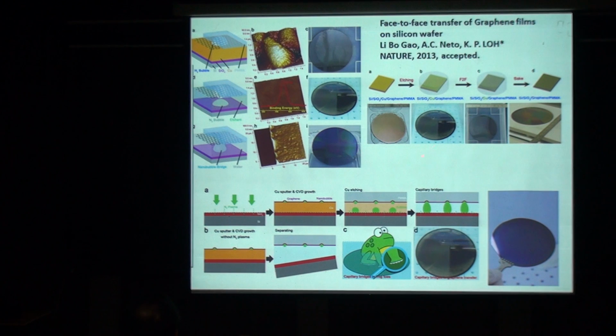Another interesting application which we just published in Nature is the fact that the bubbles have very serious implications in the adhesion of a film on the surface. You remember that if you put a plastic sheet on the table and then you have water going in between the plastic sheet and the table, you find that this plastic sheet can stick much better. It is not because water is very sticky, right? Because if you dip the whole thing into deep pure water, the plastic sheet will just come off. It is because of the air-water interface. At the air-water interface, there's a curvature, and this causes the capillary adhesion force. The same applies to the bubbles.